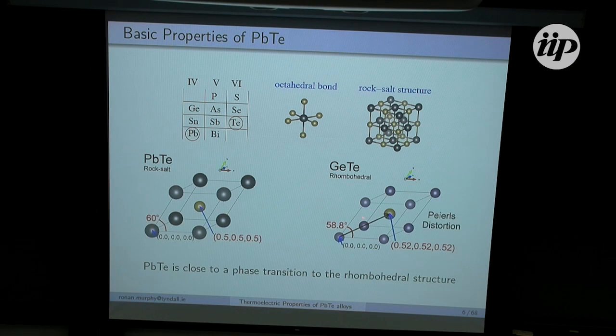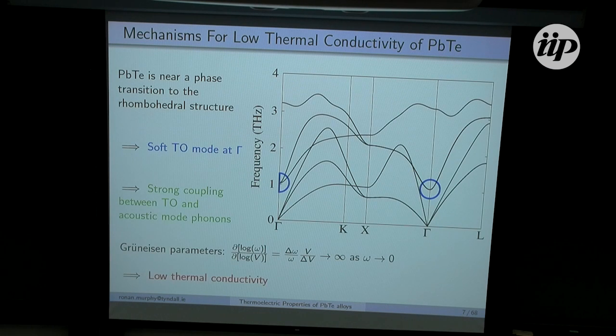Now, what I'm going to do is just compare the differences between the rhombohedral and the rock salt material, which I'm sure a lot of you already know anyway. The main difference is that this central atom here is displaced along the 1-1-1 direction, and the angle here decreases slightly as a result. This is a phenomenon known as Peierls distortion. So ultimately, the goal here is to look at the proximity of lead telluride to this ferroelectric phase transition to the rhombohedral structure, and see how this affects the lattice thermal conductivity.